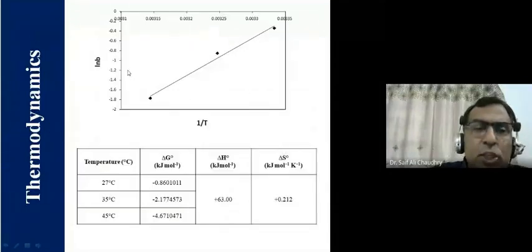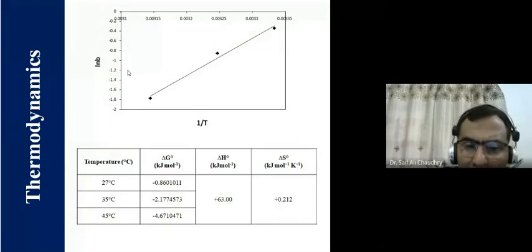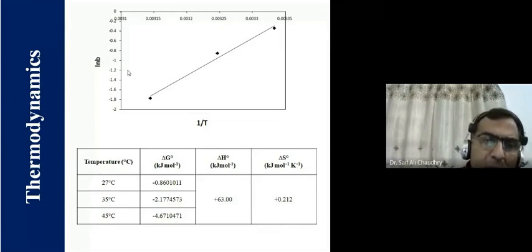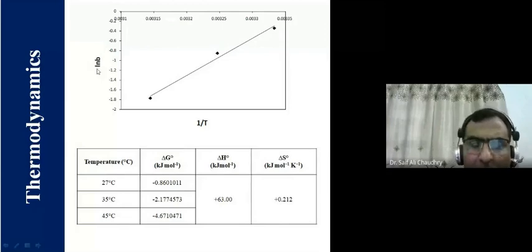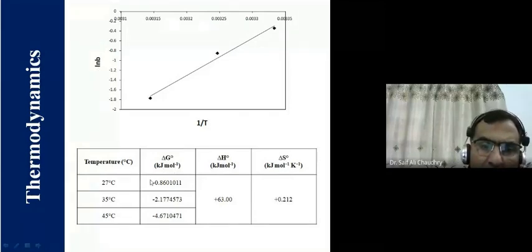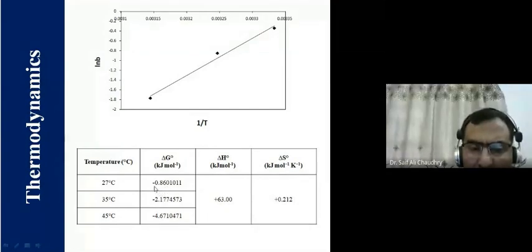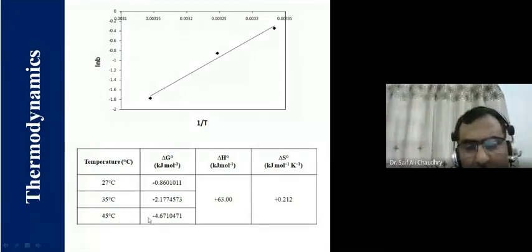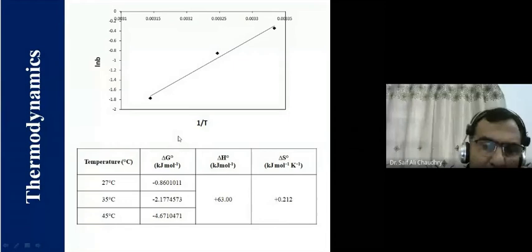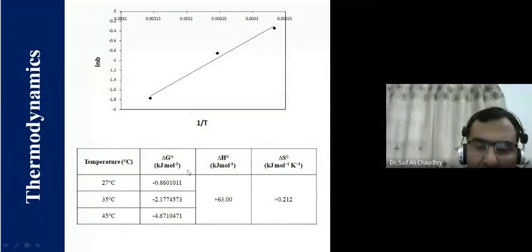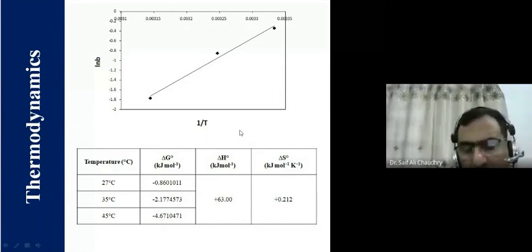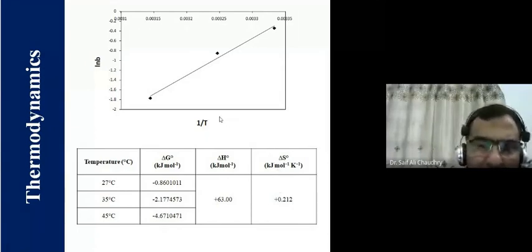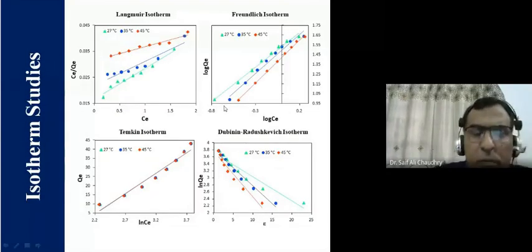Now other parameters we need to know are the Gibbs free energy change, and this is the plot between ln K in the logarithmic term and temperature, and we have got delta G that indicates negative 0.86 something. It is always negative here. At 3 temperatures we have studied, 27, 35 and 45 degrees, indicating that the process of adsorption was better at high temperature, 45 degrees Celsius, and delta H was endothermic. These parameters are required for the proposal of mechanism.